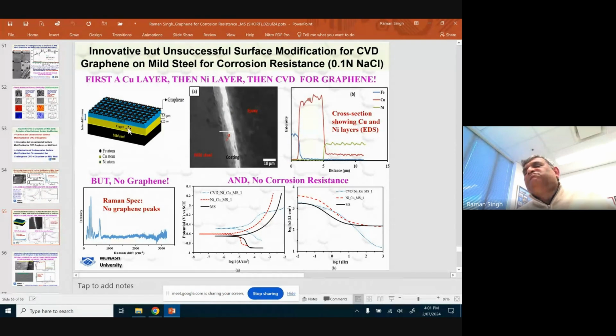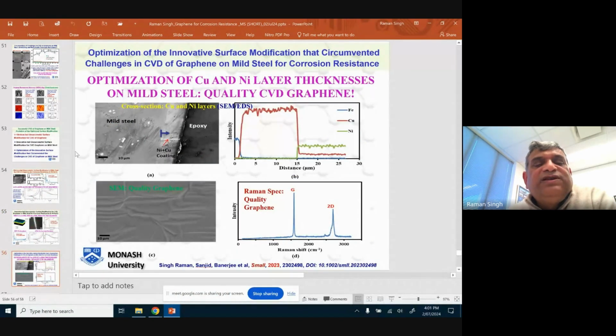So we developed a thick layer of copper and a very thick layer of nickel, and again we could not develop good quality graphene, simply because lots of carbon diffused and the carbon content of the nickel layer was so high that it defeated the whole purpose. And also a thin layer did not work. We had a thin layer of copper. I don't have time to go into details, but I will come to the real solution.